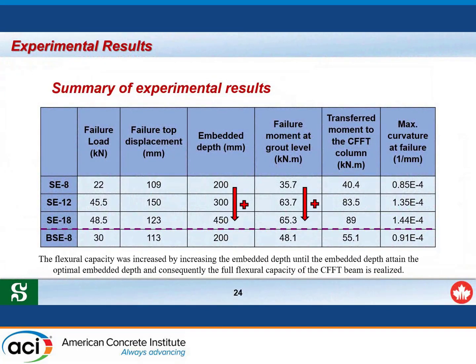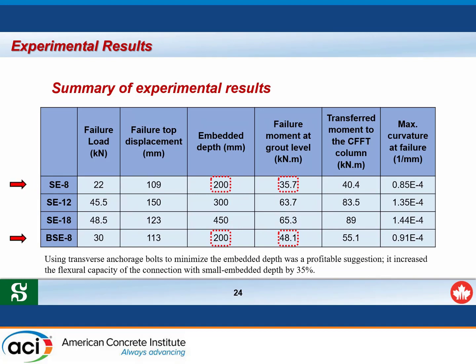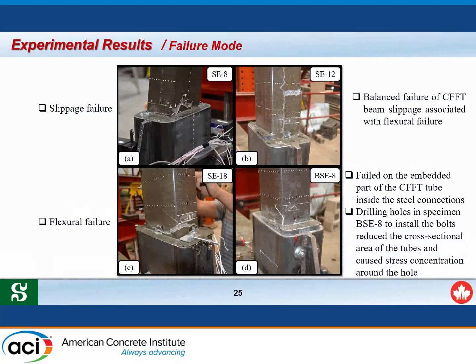The experimental results showed that, as expected, increasing the embedment length increases the moment capacity. Using the transverse anchors increased capacity by 35 percent. The smallest specimen (200 mm embedment depth) failed due to slippage, exhibiting high slippage values. The second specimen (300 mm embedment depth) showed a balanced failure — slippage occurred followed by flexural failure — indicating this depth is approximately equal to the optimal embedment depth required to achieve the full flexural capacity. The third specimen failed in pure flexural failure, and a video demonstrates this failure mode.